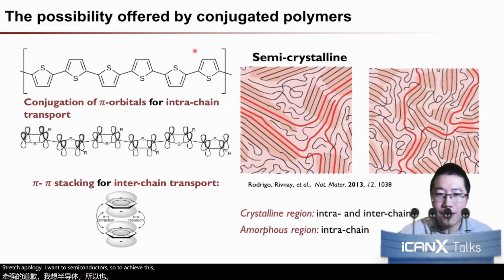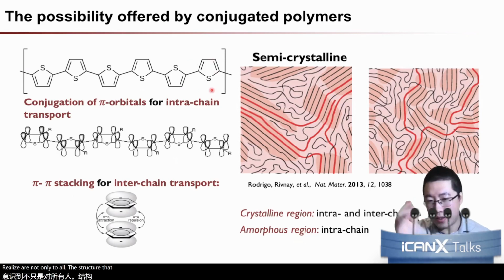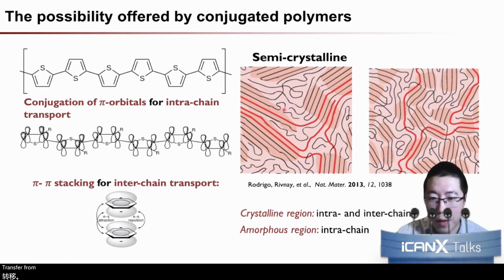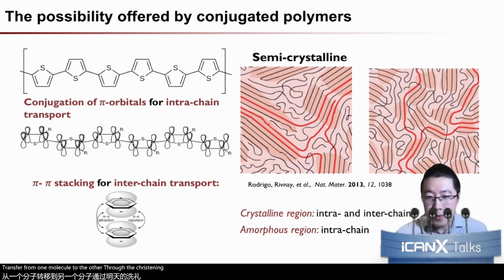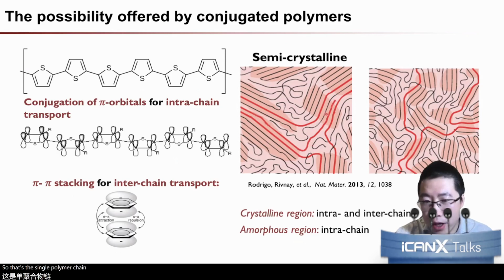To achieve this, our hypothesis is that the most promising type of material should be polymers, from the electronic transport point of view. This is because for polymers, the charge transport in the semiconductor relies not only on the ordered structure, that's the charge transport from one molecule to the other through the crystalline domain, but also, because of the relatively long polymer chain, it can accommodate a lot of amorphous domain, so that a single polymer chain can bridge different crystalline domains across this amorphous domain.